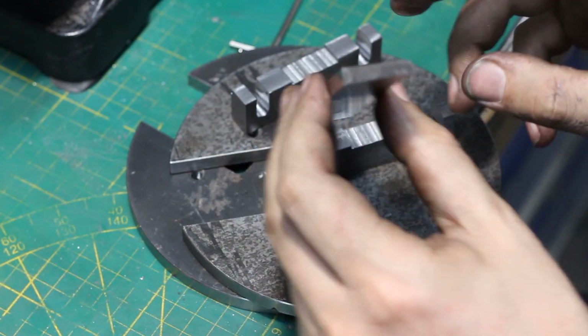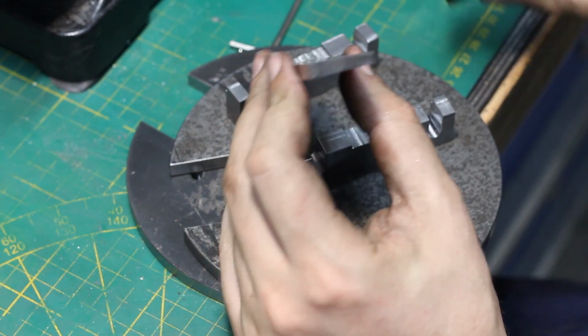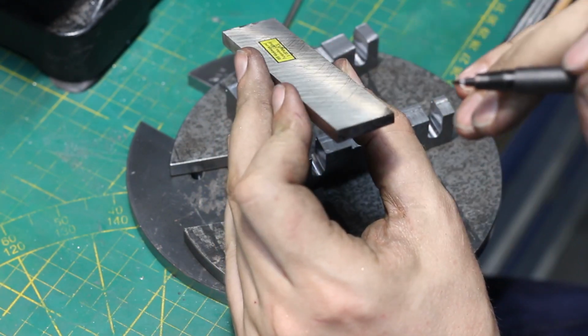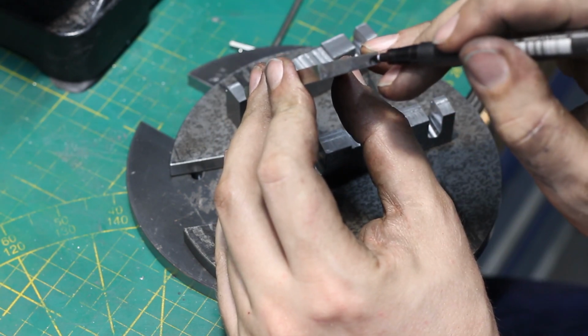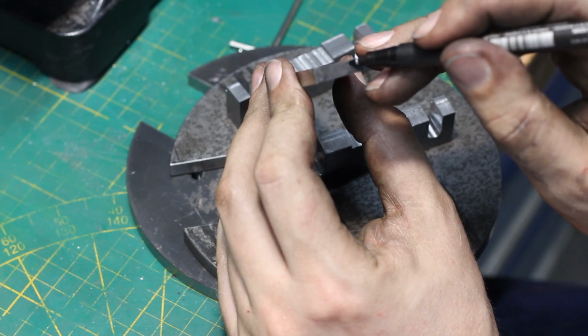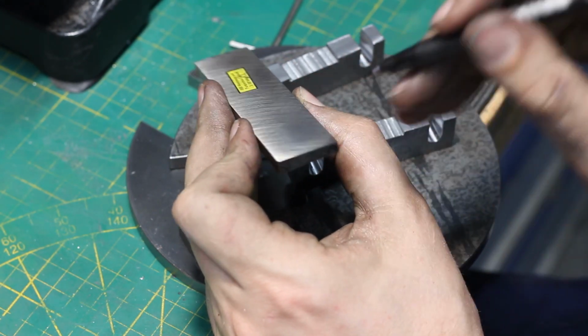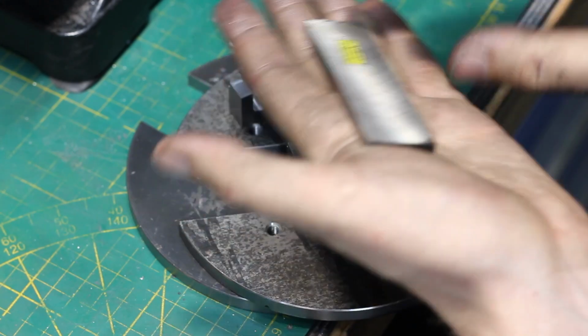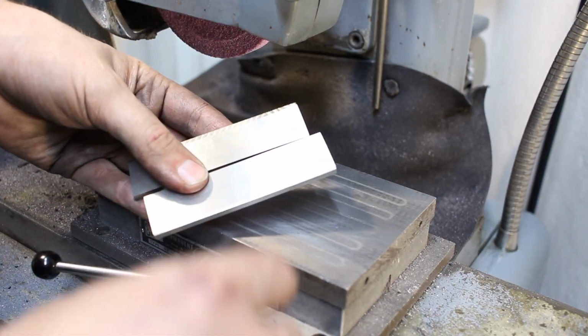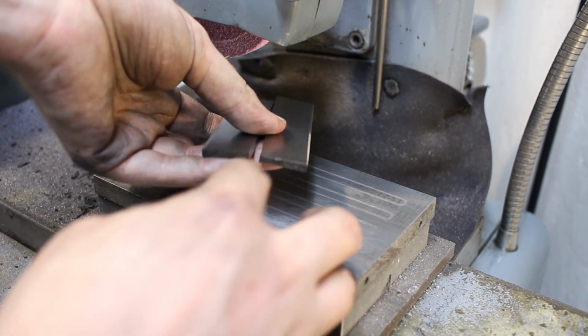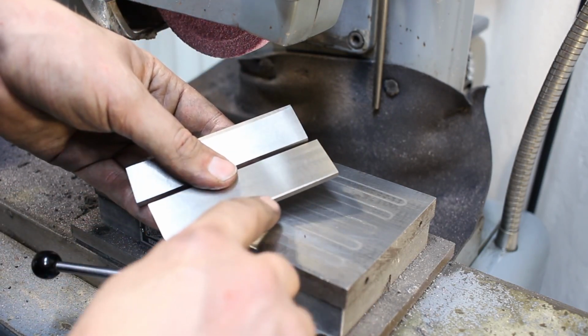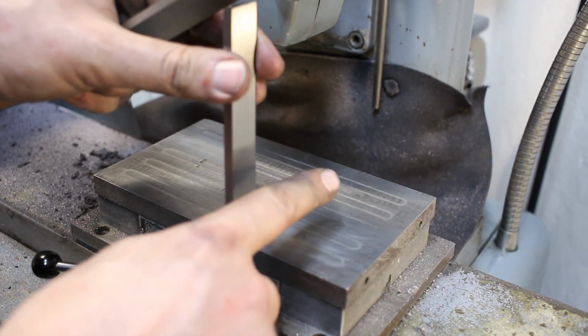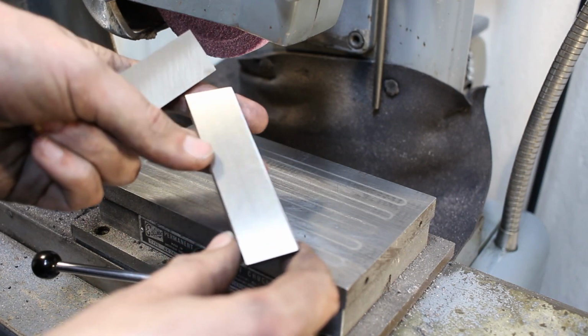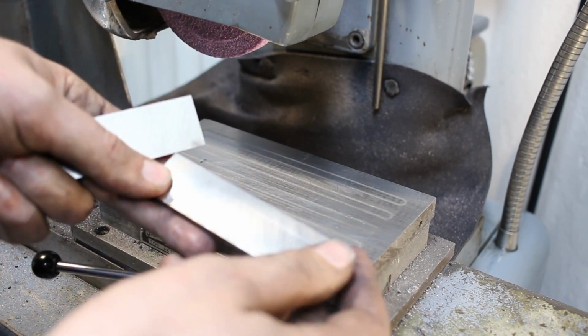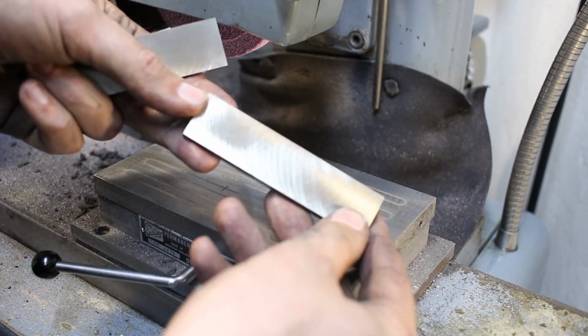Next I will surface grind these trapezoidal high-speed steel blades. They are square here and square here, but those two surfaces here and here are not parallel. So we'll put them this way on the grinder and clean them up. I already ground the taper out of the trapezoidal shape out of the high-speed steel blanks. Didn't clean them up completely, there is a little bit left here, but this side gets silver soldered into the block, and this side is where the belt runs over. So this has a Blanchard ground finish as usual.